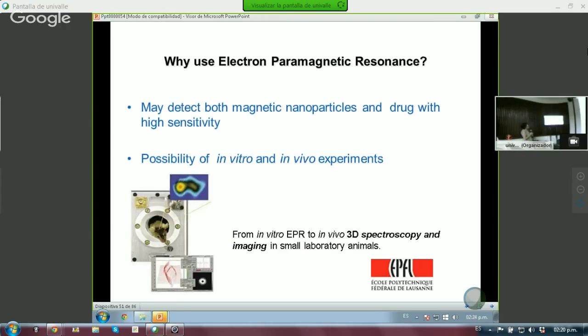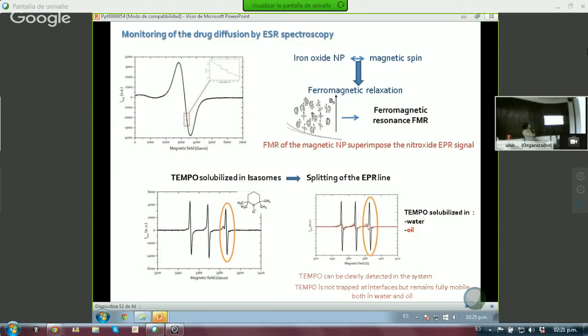Okay, and in this case we use electron paramagnetic resonance, or ESR, electron spin resonance. It's kind of the same thing. And we use it because we could detect with it both the magnetic nanoparticles and the drug with a high sensitivity. And we also explored the possibility of having in vitro and in vivo experiments. And in this case, the PhD candidate was very lucky, because she had to go to Switzerland and do these measurements at Lausanne at the EPFL with our collaborators, because we don't have all the equipment. And here is a summary of the interesting results that she obtained there.